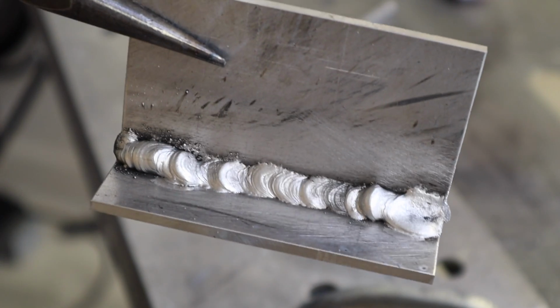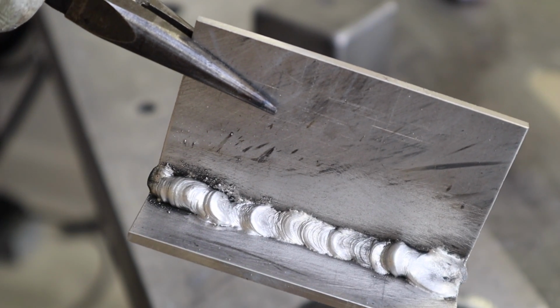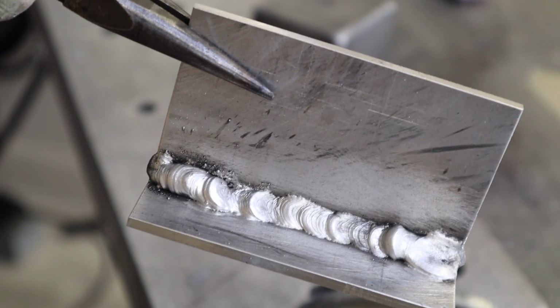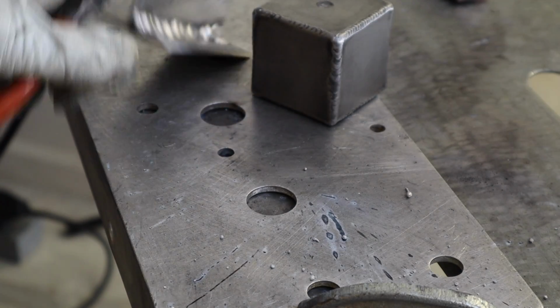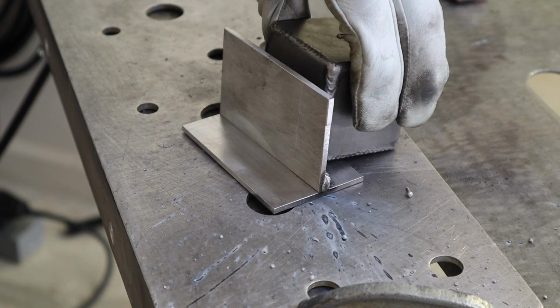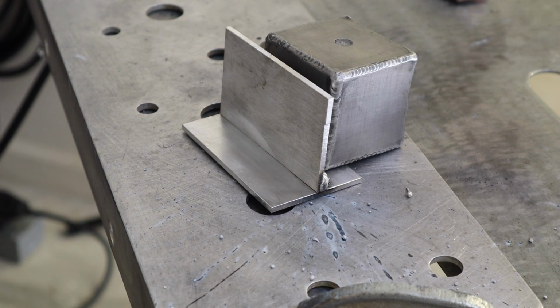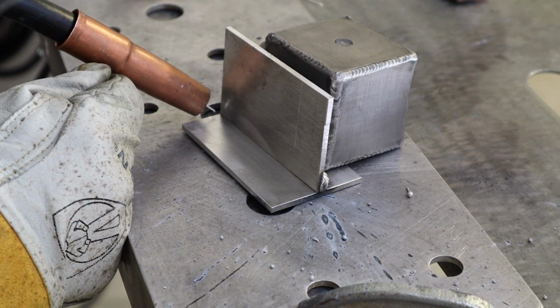I think that's due to a couple of things. One, I think I could increase my wire feed speed and maybe prevent that. And two is I'm not holding, in some cases, enough stick out. Aluminum requires about a 3/4 of an inch stick out so that you don't get that burn back and weld the aluminum wire to the contact tip. So I'm trying to get used to that and just trying to learn this process.